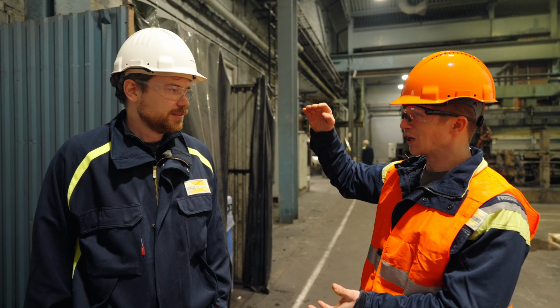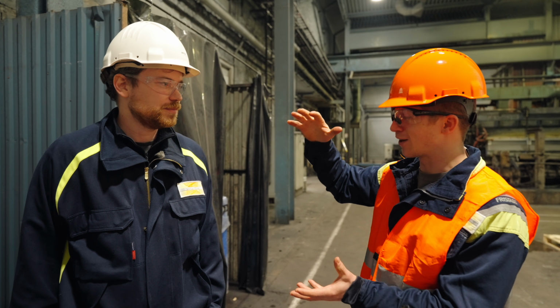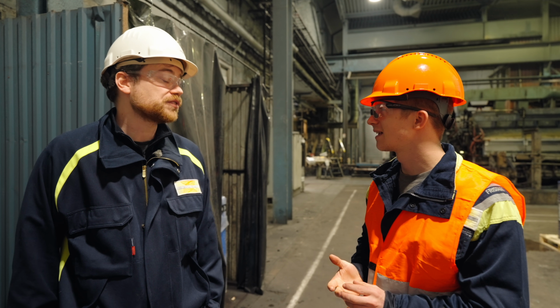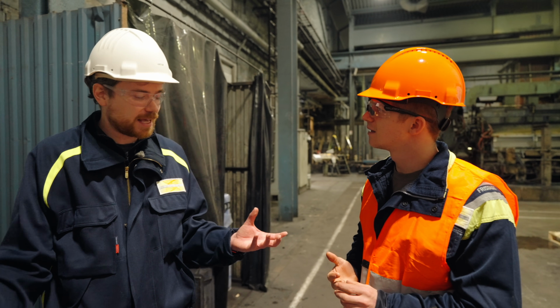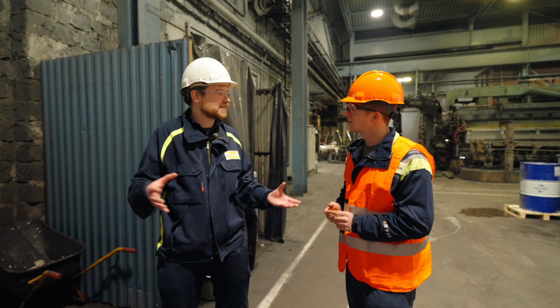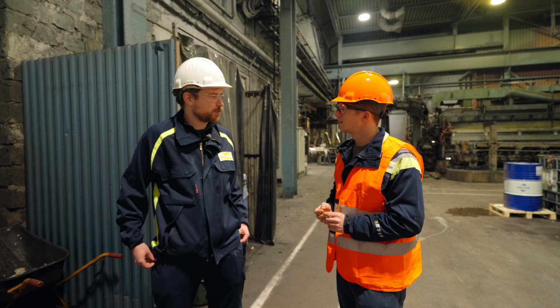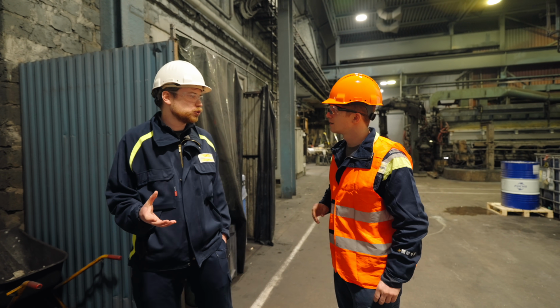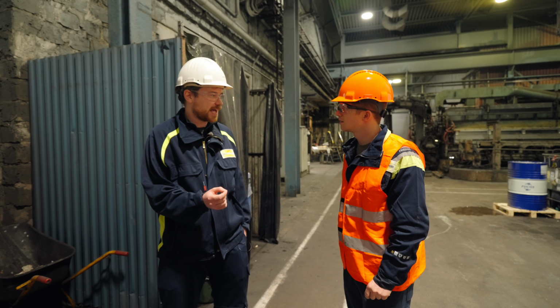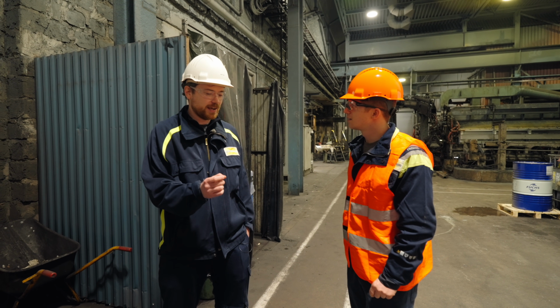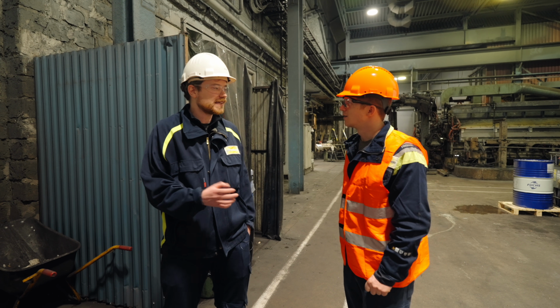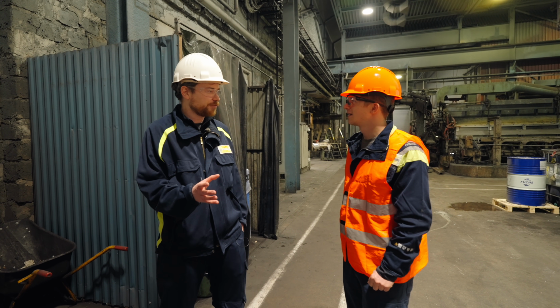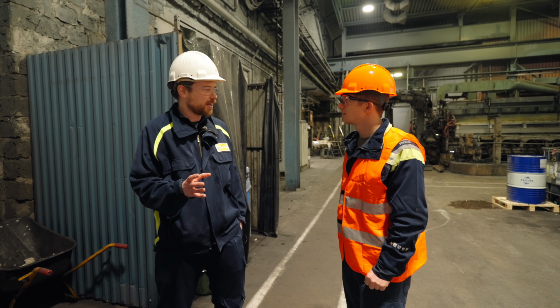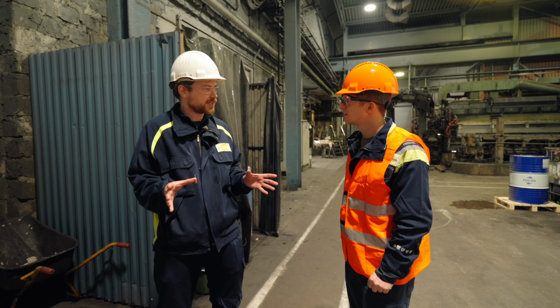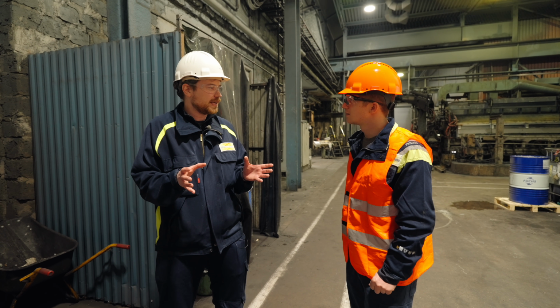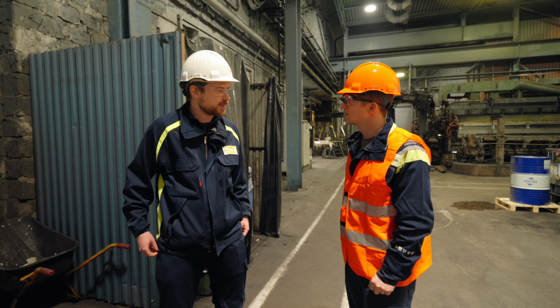Okay, so it's going to be going from liquid to solid over that time. Yes, and it gives lots of time for diffusion to happen, which means that alloying elements will clump together and form these stringers and large carbide networks that we want to avoid. In the powder process, we're basically making tiny ingots at a fraction of a second. So it goes from liquid steel to solid in less than a fraction of a second. Okay. So there's no time for diffusion to happen, and all of those alloying elements are locked in perfect dissolution throughout the steel. All the alloying elements are perfectly spread out in the steel.